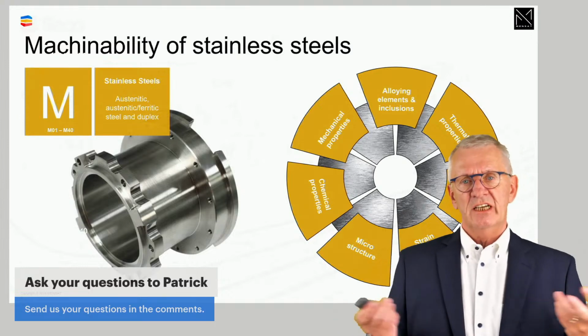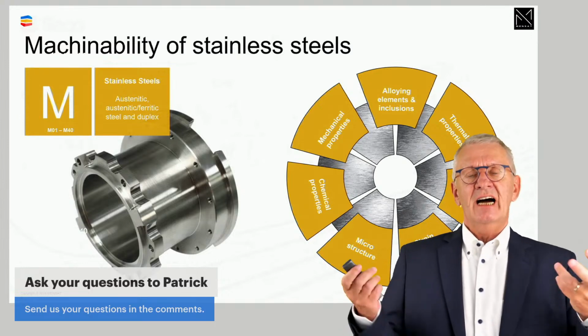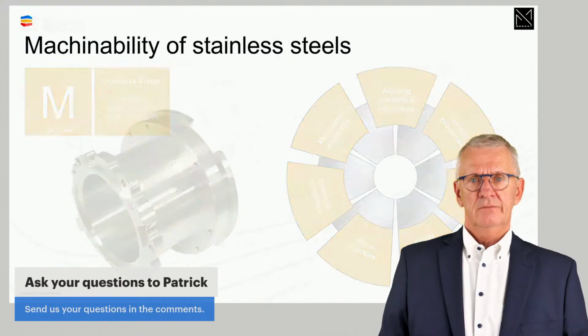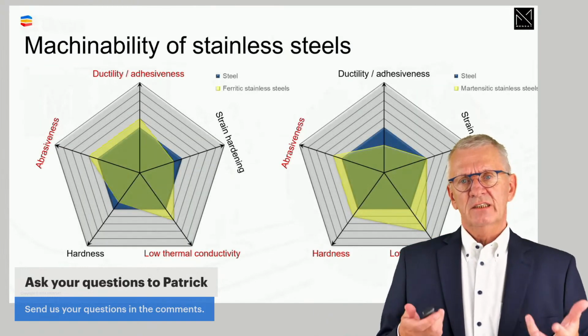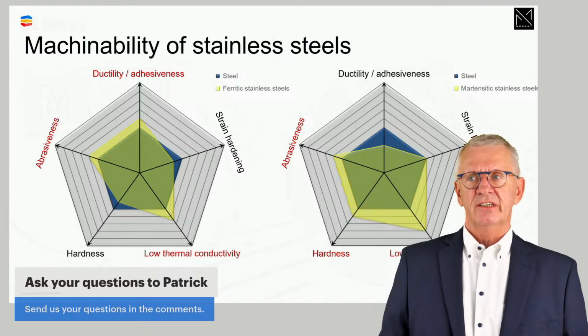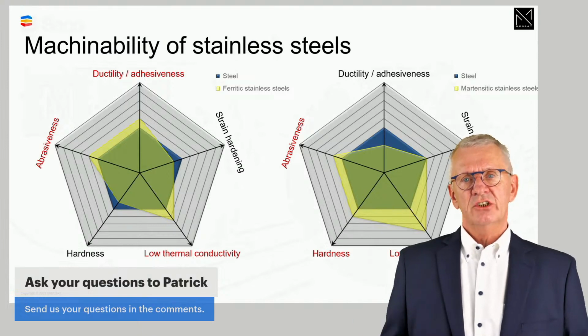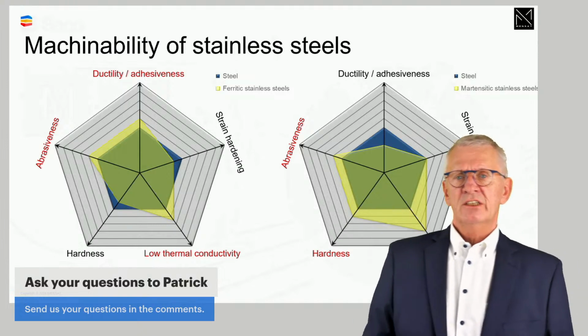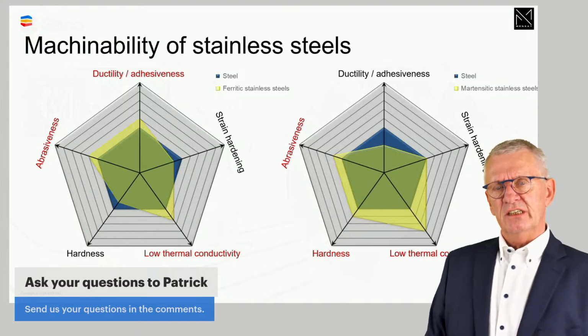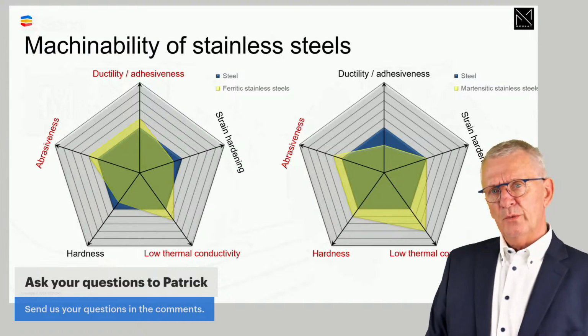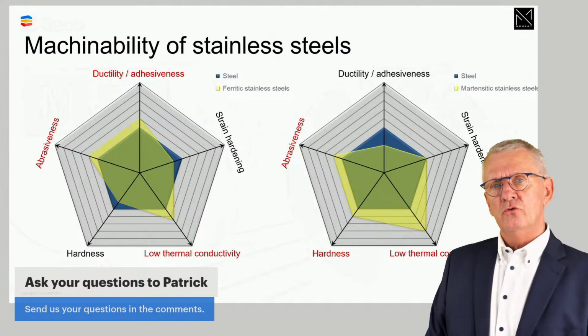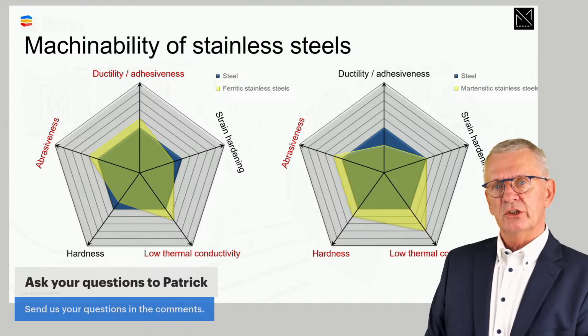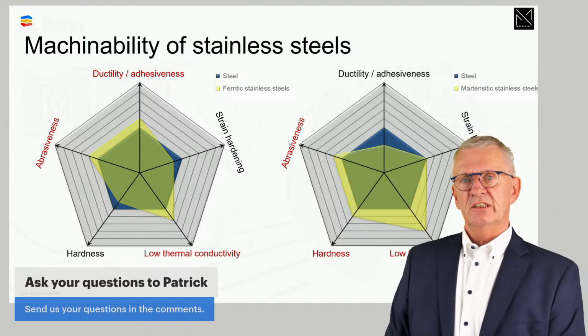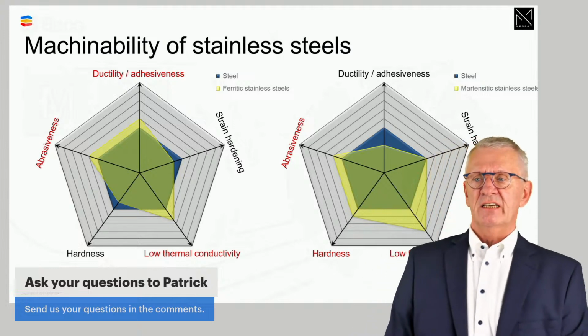Now, if I look at stainless steels, they have a certain structure, they have alloying elements, there are mechanical properties, and so on and so forth. It's the ISO M group. But if I try to put it in the 5-dimensional thing, if I look at ferritic stainless steels here to the left, or martensitic stainless steels to the right, what you see is, if you compare it with traditional steel, the blue thing, for the 5 properties, imagine I take steel as a known material. I know the tools, I know the cutting conditions to give good results. And if I compare the 5 properties then, well, here you see ferritic stainless steels.